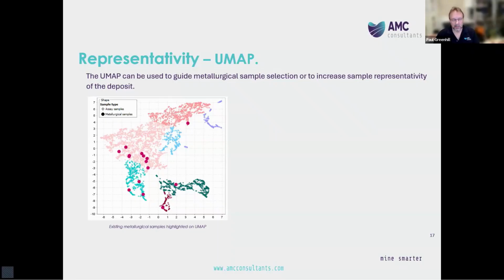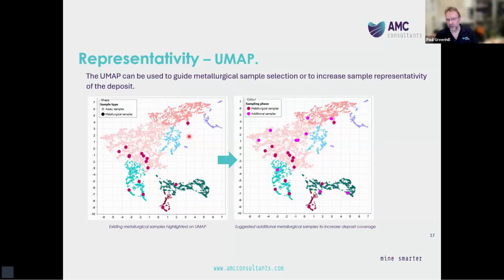But you can also see that there are significant areas within this projection where there are no samples being selected. And interestingly enough, you can see that there are circumstances where, for whatever reason, within this projection, there is a single isolated sample that has been selected. So what that allows us to do is suggest where we might add additional samples. And on this, we have added recommended samples to the metallurgical sample set. And the objective here in this case, in the absence of other information, was to ensure that we had a reasonable coverage of the variability of the deposit as it's interpreted using this sort of multivariate analysis.